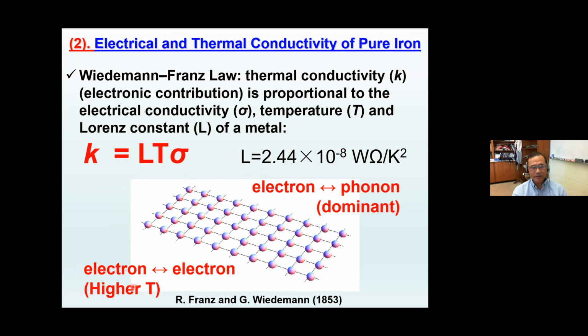At higher temperatures, though, you can also have electron scattering that contributes to the thermal conductivity. So you would actually expect the Lorenz number to deviate from the ideal value here. And similarly, if you now add light elements into the system, the thermal and electrical conductivity of iron alloys may not follow the Wiedemann-Franz law.